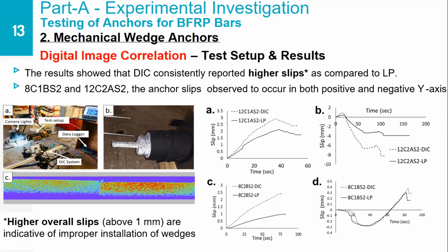And also we have noticed that if you look at these slip variations with time, for 2 of these specimens, we could observe negative as well as positive slips. This was because of the initial setting of the bars inside the anchors, because of which there was some reverse movement of the bars with respect to the anchors, which caused the negative as well as the positive slips to be recorded in these measurements.